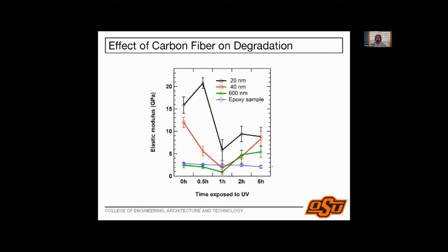If you start with the blue line first, I take an epoxy sample, no carbon fiber, no interface region. I expose it to UV, and there is a slight decrease in elastic modulus as time goes on. Chain scission, we understand exactly what is going on. If I take bulk polymer that is in a composite, so I'm sitting at 600 nanometers, the initial behavior is the same as what I expect in the case of bulk polymer. But after about 1 hour, the behavior of the bulk polymer region in the presence of a carbon fiber composite is different than if it was just purely a polymer.